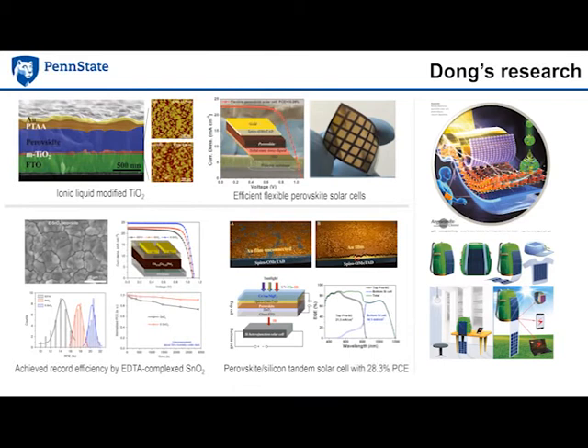Another work I would like to highlight is another surface modification, but it's more advanced. Here they use tin oxide rather than titanium oxide because it's highly conductive compared to titanium oxide. By using these EDTA molecules to optimize the surface properties of these layers, they're able to get very high efficiency, over 20% power conversion efficiency. And most importantly, by this modification, the device has very good stability compared to the previous pristine devices.